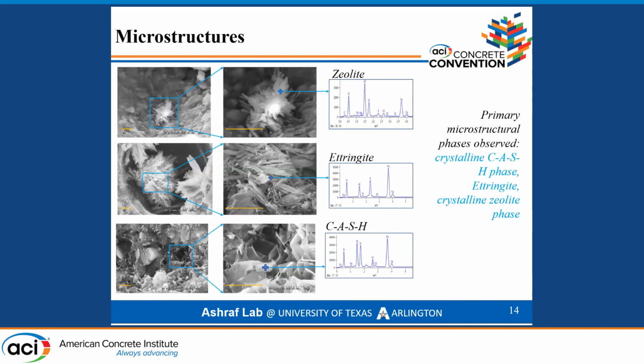Let's see some morphology of our crystalline products. We used SEM EDS to determine these morphologies. The first image is a bunch of crystalline needles, which represents some crystalline zeolite. The second bunch of needles is ettringite. We can see the presence of sulfur from the EDS spectra, which proves the presence of ettringite. Then we have some crystalline calcium aluminum silicate hydrates. All of these phases were also present in our ancient Roman concrete samples.